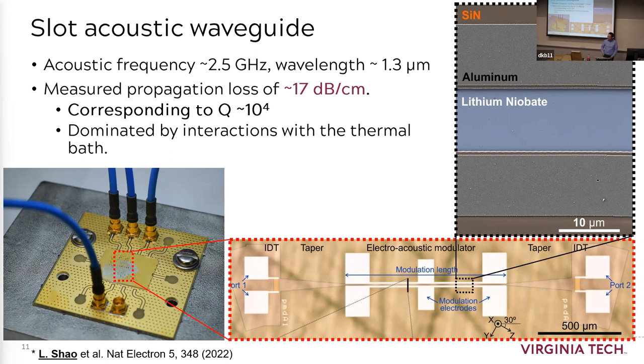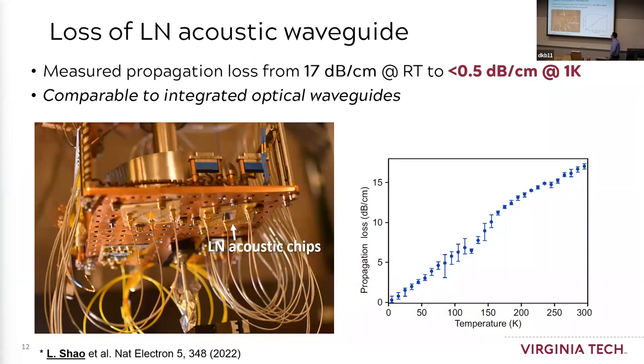And we are also wondering what is the mechanism of this acoustic loss. So we came to the conclusion that this loss is actually dominated by the interaction with the thermal bath, basically the thermally excited phonons at room temperature. So how we know that is we put this device into this fridge, which can cool down to a temperature of only 0.9 Kelvin, but we have another one in our lab, we can go to 10 millikelvin.